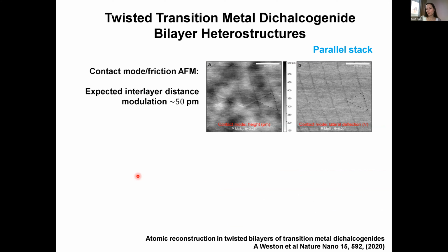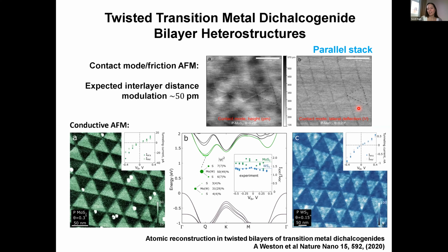So we tried to use the AFM, atomic force microscopy. However, this is really on the edge of what is possible with atomic force microscopy measurements. So you can maybe see that in the parallel stacked regions, we're starting to see some sort of triangles, but it's really not terribly convincing. So instead, we looked at conductive atomic force microscopy. And here the domain structure really lights up like it did in the transmission electron microscope.